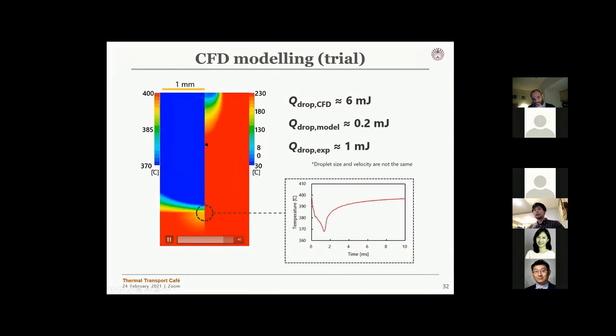So the droplet behavior looks okay if I compare it with the experiment. And the temperature variation seems, well, I couldn't say reasonable because this is not a very realistic model, but we can actually quantify the temperature variation within the substrate.